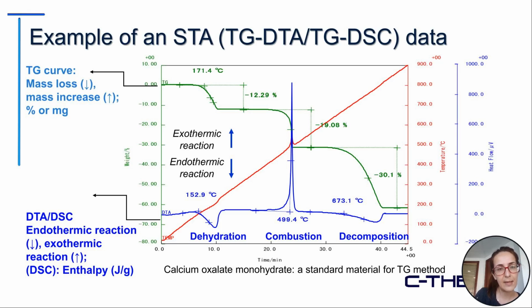Here you can see an example of STA data. This data comes from calcium oxalate monohydrate, which is a standard material for the TGA method. In this thermogram, you can see the TGA and DTA curves. The green curve is related to the TGA analysis and the blue curve is related to the DTA analysis. In TGA, we can see three mass losses. The first mass loss is due to dehydration, or loss of water, which corresponds to the endothermic peak in the DTA analysis.